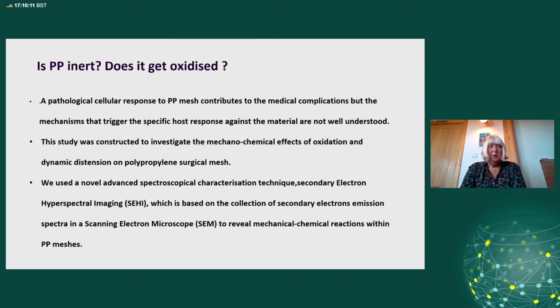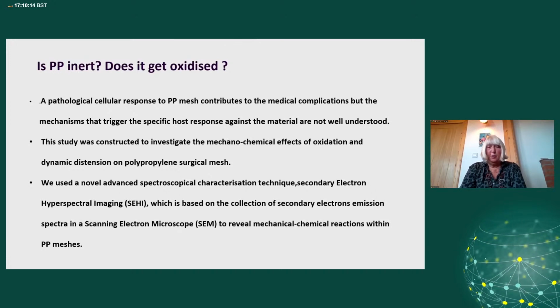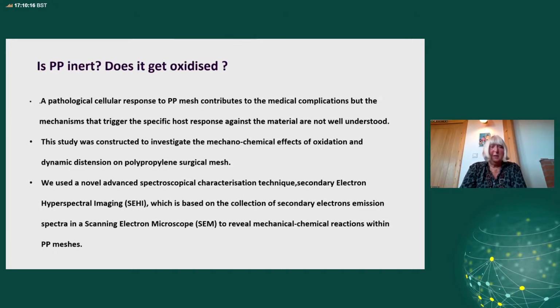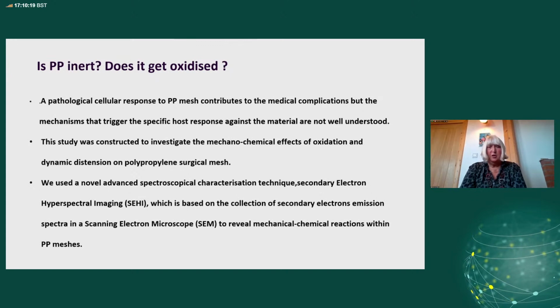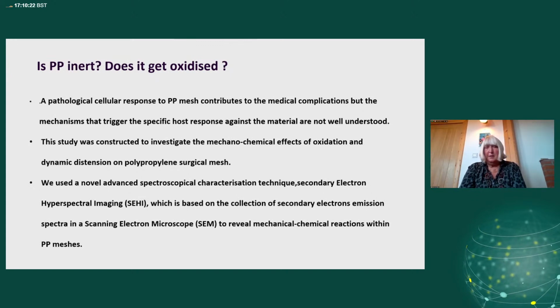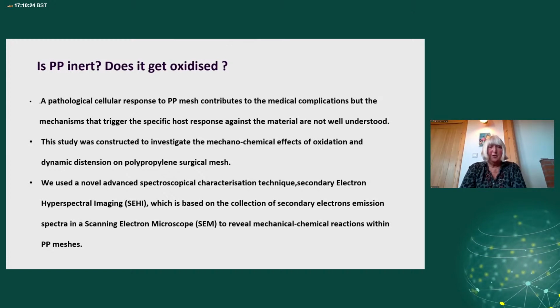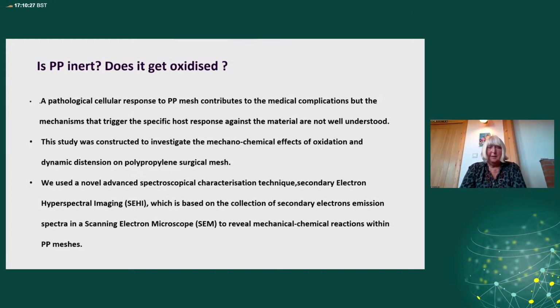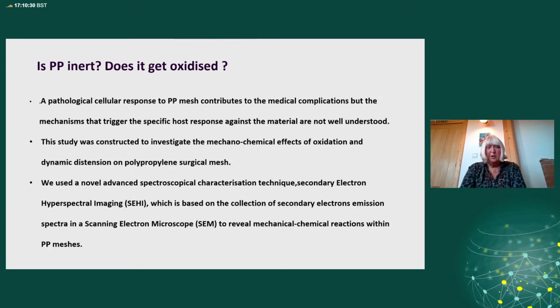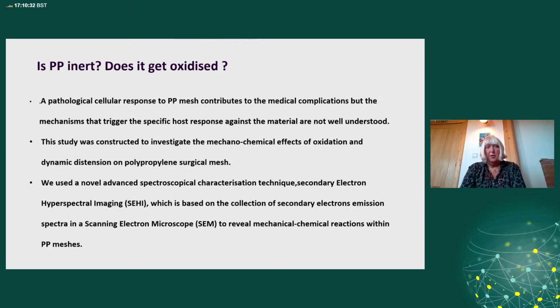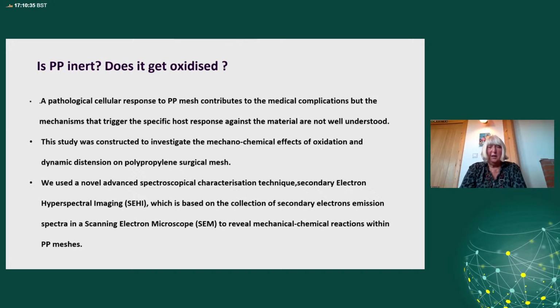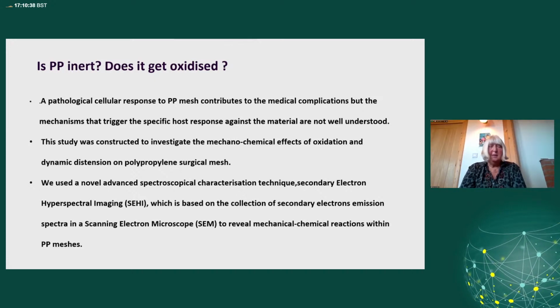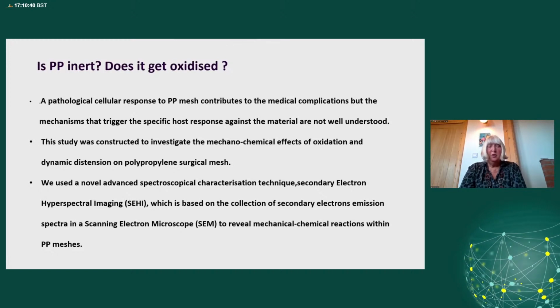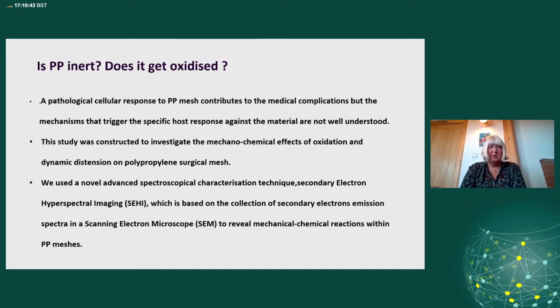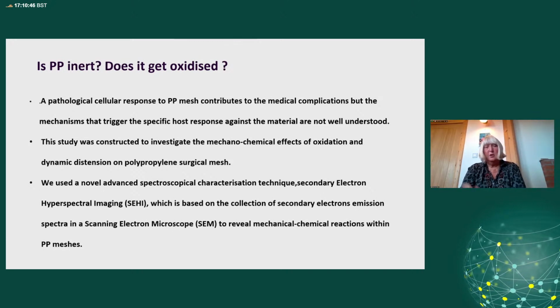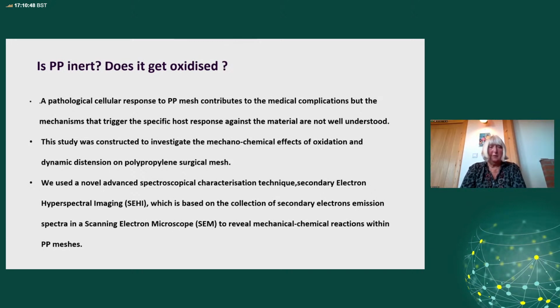So we know that there's a pathological cellular response to polypropylene mesh that contributes to the medical complications, but we're not really sure what triggers it. Is it some change at the surface of the fibers? So we designed this study to look at the effect of mechanical stress and oxidative stress. Now, for oxidative stress, we used exposure to hydrogen peroxide for a number of hours. This is a standard ISO test that you use when you're deliberately fast aging materials. So we looked at mechanical distension and oxidative stress, separately and together.